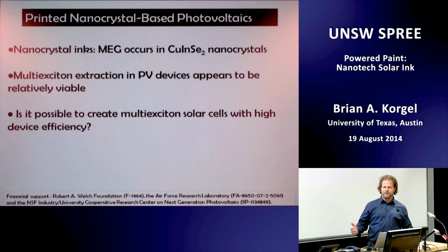But I would love to be able to do that. It's a really hard challenge. I would say in terms of using nanocrystals as photovoltaics, seeing where the field has come, just even in the last 4 years or so, it's pretty remarkable. Going from where the record efficiency was, 2.5%, now as printed devices are above 8%, and with lead sulfide, people understand how to tune the electron affinities of lead sulfide nanocrystals by changing capping ligands and playing games with those.